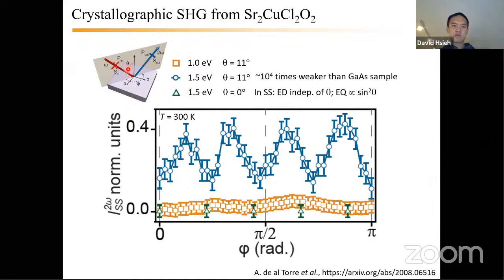You can sort of reason to yourself, right? The process is P equals chi EE, and that doesn't depend on theta. And so you would expect that if you're looking at the surface, you would have no theta dependence. Whereas if you're looking at the electric quadrupole channel, where there's a gradient, so there's a factor of the wave vector in it, then that will depend on angle of incidence. And at least in the reported point group, that should scale as sine squared theta. So it should vanish at normal incidence. And indeed, we see that, if we've done an angle of incidence dependence measurement, that vanishes once we go to normal incidence. So we're pretty confident that what we're seeing, at least at room temperature, is this resonantly enhanced bulk SHG process coming from a bulk electric quadrupole radiation channel. Okay, so that's what gives rise to these wiggles here.